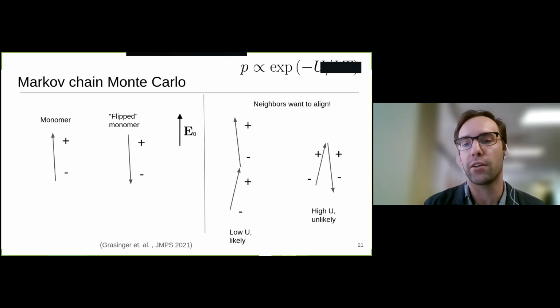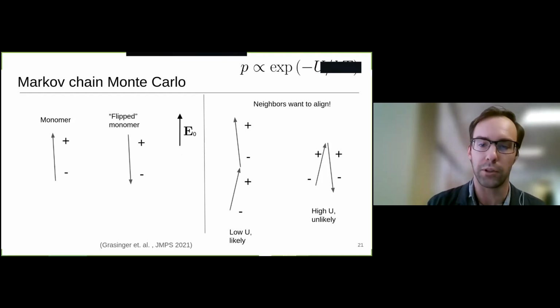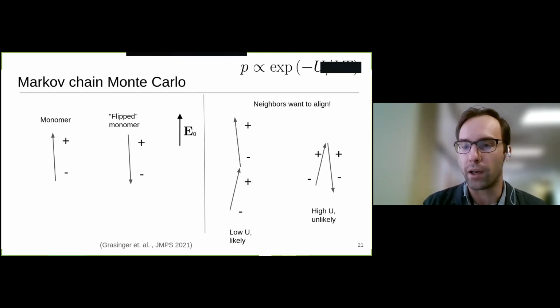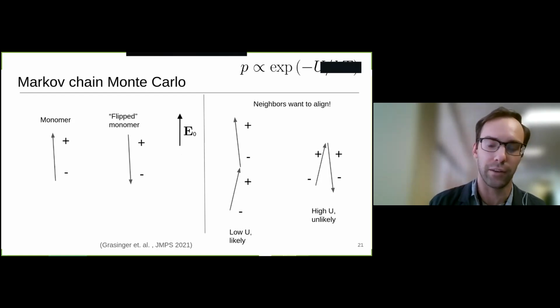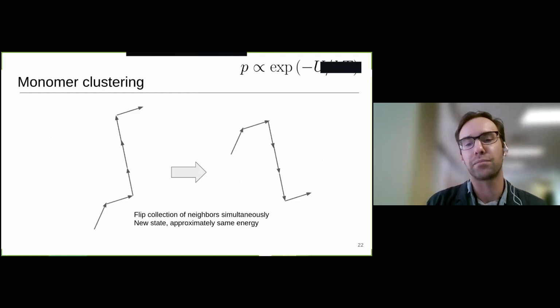But the issue here is that neighbors want to align. So if I pick out one particular monomer and I try to flip it, I go from this case, which is very nice and energetically favorable, very low energy, so I have positive charges next to negative charges. If I try to take this top one and flip it, now I'm putting positive charges next to positive charges, and negative next to negative, which is bad. It's a very high energy state.